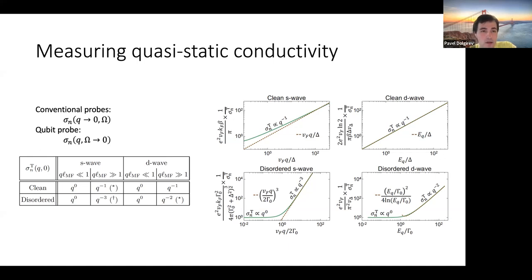And so qubit probe indeed provides you with very different possibilities compared to conventional probe. And because of this new feature of NV centers in particular, one may ask, can I send omega to zero and study what are the possible transport regimes? And in fact, this way we discovered that, for example, disordered S-wave and disordered D-wave are very different because at large q, you see either scaling q^-3 or q^-2. So both are, in principle, accessible to qubit sensors.